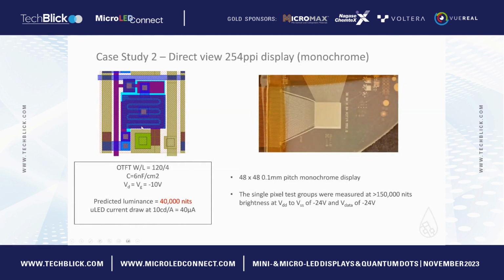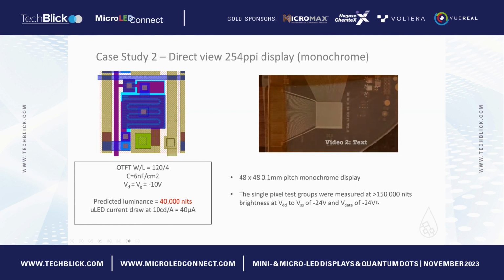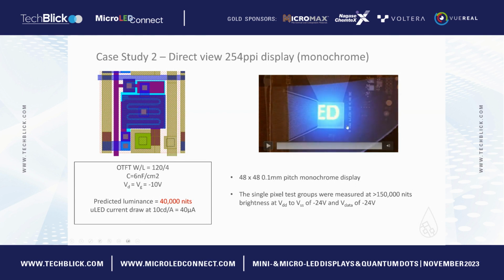The second one is the higher resolution 254 ppi. This has a W over L in the transistor of 120/4, and this can generate around 40,000 nits, as you can see here from this image. We can get higher brightness with higher voltage, but generally the operating voltage of driver chips is typically a lot less, so you don't want to go to such a high voltage, but still 40,000 nits is more than enough brightness for a number of applications.